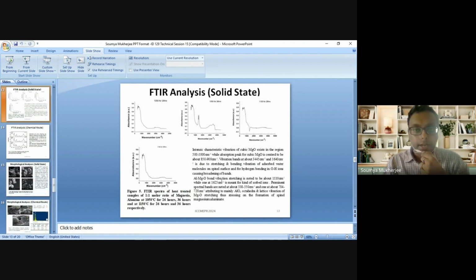So this is the FTIR analysis. The FTIR analysis clearly indicates the spinel formation, where the inorganic parts come below 1000 cm^-1. We are getting the existence of cubic magnesium oxide in the range of 500 to 1000 cm^-1, and we are also getting the alumina magnesium oxide bond vibration close to 1100, along with some sorbed ions from moisture, which is possible due to the atmosphere, since the FTIR was carried out in air, not in a nitrogen atmosphere.